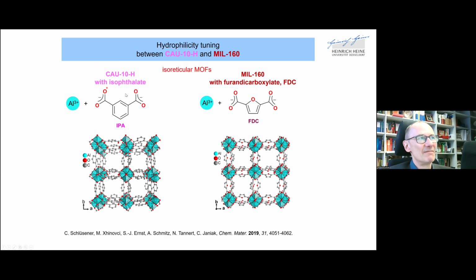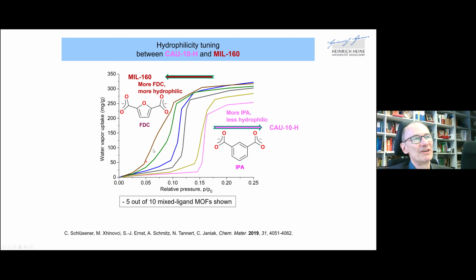So here we have aluminum CAU-10-H with isophthalate and the aluminum MIL-160 with furan dicarboxylate. The linkers have a similar bent topology, and you can partially replace the isophthalate linker with a furan dicarboxylate linker and vice versa, and keep the same aluminum MOF structure with these rectangular or square channels. In doing so, you fine-tune the water uptake curve. In pink is shown the pure CAU-10-H MOF with the one linker only, and in brown is the MOF MIL-160 with a single linker.